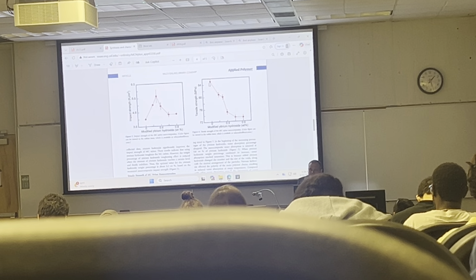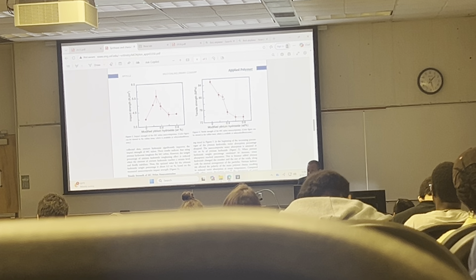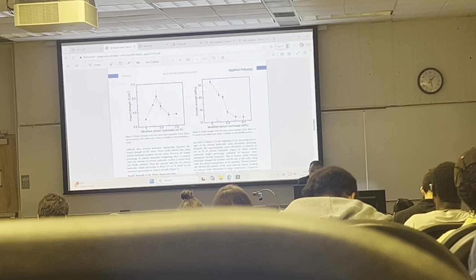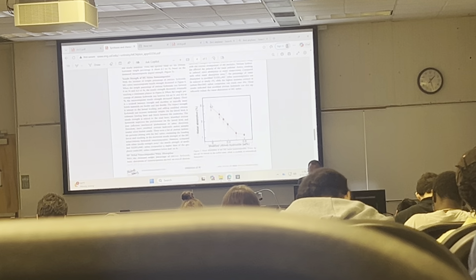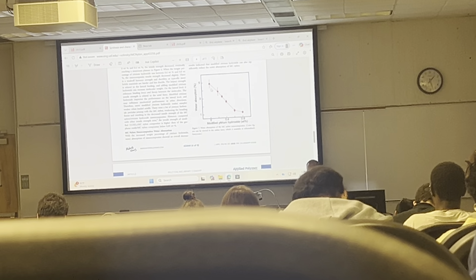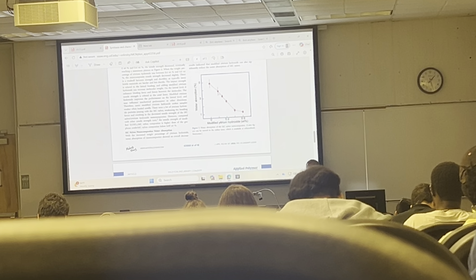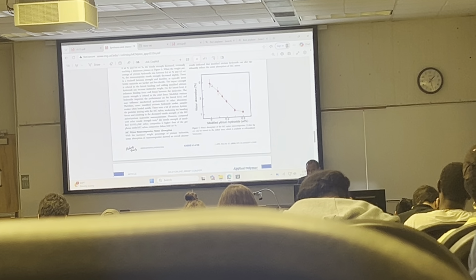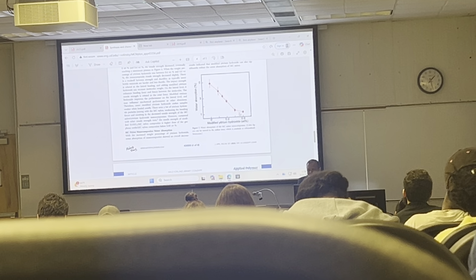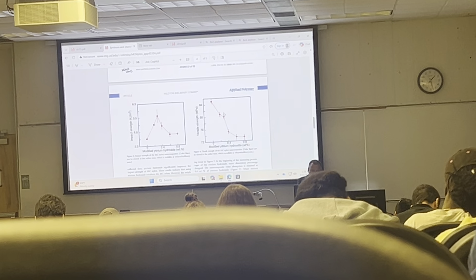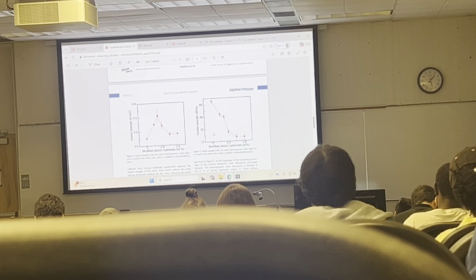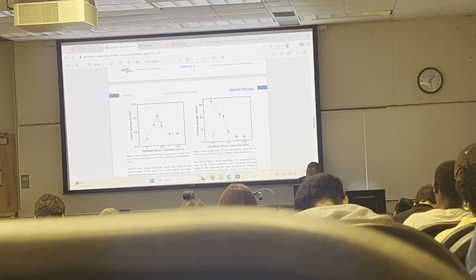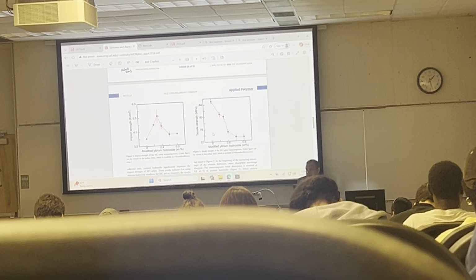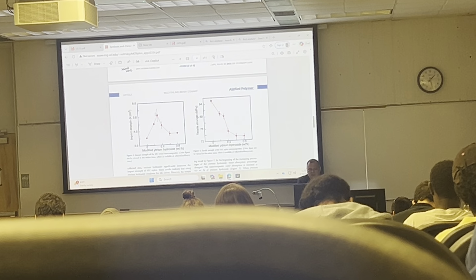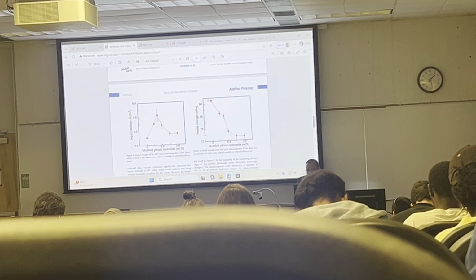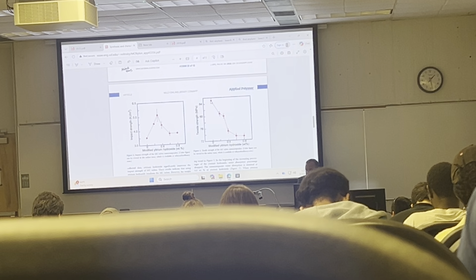what it also does is it drops down the tensile strength. So here is an example of the optimization based on the two mechanical properties, the impact strength and the tensile strength. And the other parameter was, in this case, water absorption. So the problem is the more fibers you add, well, actually this is good. The lower moisture absorption is good. But the tensile strength goes down. There are some good systems where we just take one parameter and it affects the properties in a good way. But here you can see the impact strength, this is the optimal, and over here in terms of the tensile strength, it's better not to add anything at all.